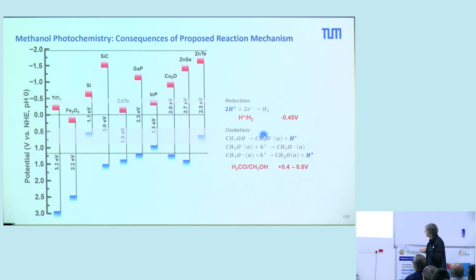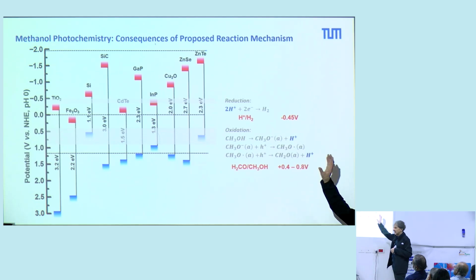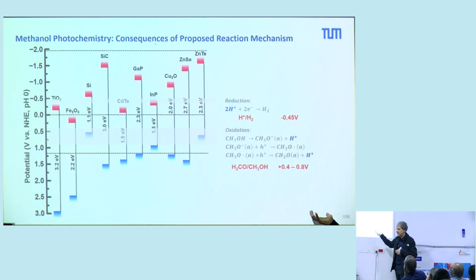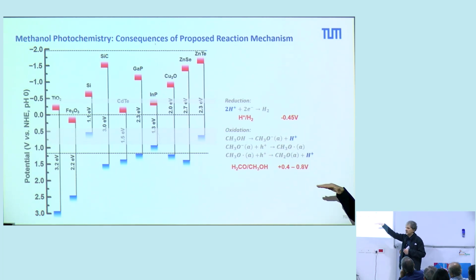For the alcohol oxidation, this is shown here. This is the oxidation, and here we have the reduction potential. And so titanium wouldn't work, for instance, for the alcohol oxidation. You need other oxide materials. But our mechanism showed that the conduction band is not relevant because we don't have this reaction. We have a thermal process, a recombination of this hydrogen. That means in our case, we only have to tune the upper edge of the valence band. And of course, we have to tune the chemistry on the surface. This is more relevant than the electronic structure of the semiconductor. And this opens a new materials space to design photocatalysts.